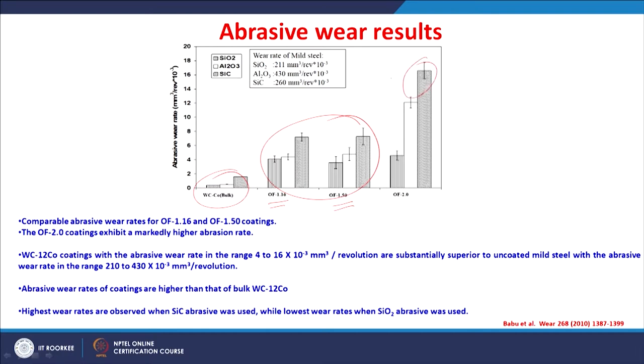With respect to the abrasive used, the silicon carbide abrasive always gave a higher abrasion wear rate, whereas the silicon oxide abrasive always gave a lower abrasion rate. In addition to that, one important point is that for tungsten carbide cobalt coatings, the abrasive wear rate is in the range of 4 to 16 × 10^-3 mm³ per revolution, which is substantially superior to the uncoated mild steel with an abrasive wear rate in the range of 210 to 430 × 10^-3 mm³